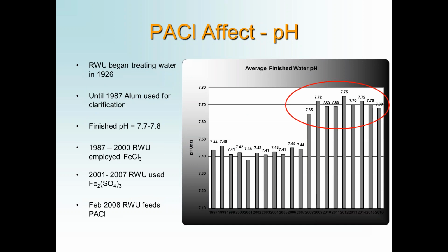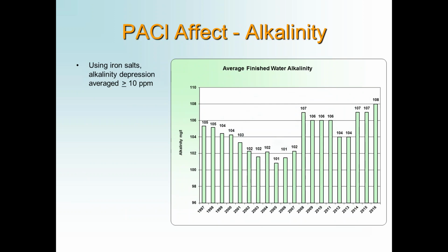Iron salts depress pH more, and you can see from this graph, which goes back to 1997, but before then too, from '87, the pH of our finished water leaving into the distribution system was around 7.4, 7.5. And with the switchover, we immediately noticed a rise in pH. Typically now our finished water pH averages about 7.7, which obviously, as Darren explained, higher pH equals less corrosion. So there was a big benefit right there. Again, this is all happening in 2008.